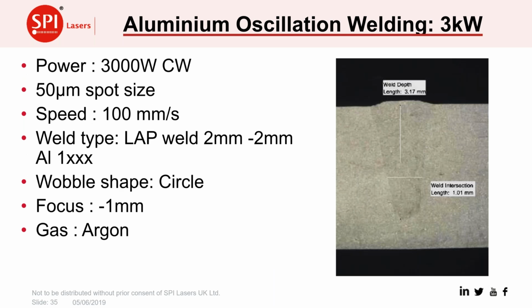We went up to a 3 kilowatt laser. This time we've increased the spot size on the aluminium. We're using a slightly bigger spot size than we did for the copper, and that's been found to be advantageous to the type of weld and the quality of the welds that we get. This is actually a lap weld, 2 millimeters top and bottom, and you can see we've penetrated over 3 millimeters, and that we've got a good 1 millimeter weld width at the intersection, so we've got a very strong weld produced here at quite a reasonable speed. So it's using a 3 kilowatt laser.